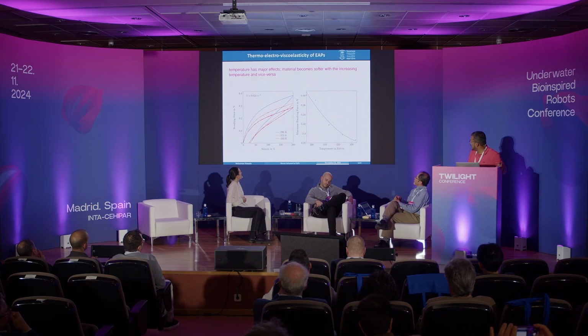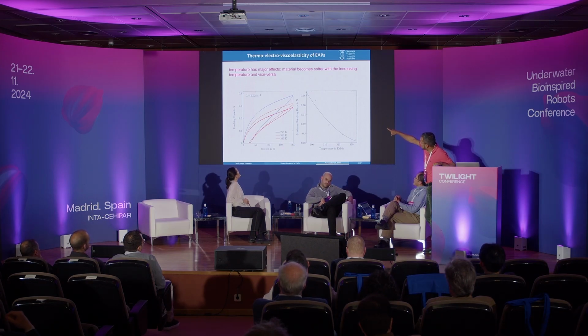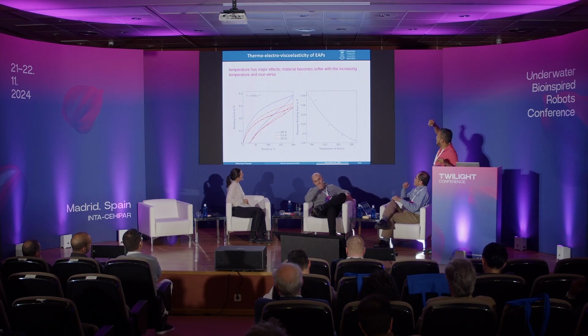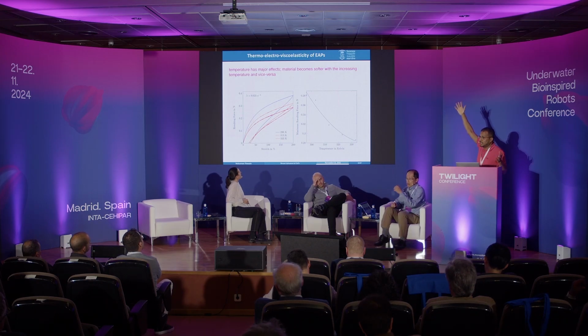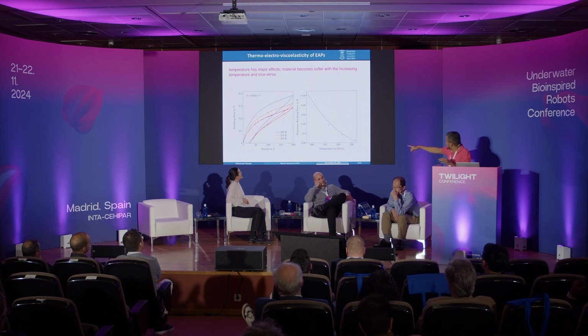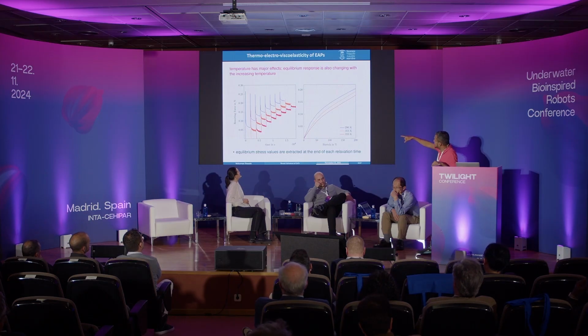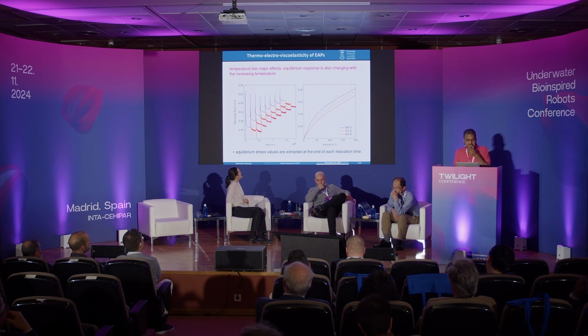So if you increase, this is the temperature. I'm sorry, this is only a fixed strain rate, but with temperature. Look here. So at 20 degrees centigrade temperature, this is 0.8. And then when you have 40 degrees centigrade temperature, it's almost double, right? 0.8 to 0.36. That means with the temperature increase, you are getting less force or less stress. The same thing happens if you apply the temperature during your relaxation test: you are getting less response if you increase the temperature, and so on.